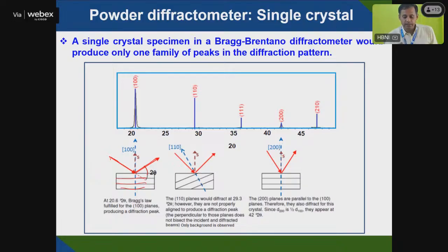A single crystal specimen in Bragg-Brentano diffractometer would produce only a family of peaks. You are getting a peak here, this peak is 100. Then you are getting a peak at 200. You are not getting 110, 111, 210, so they are empty; there is no peak there. Because only one plane is oriented to the X-ray beam, you are getting the 100 plane. Similarly, you will also get its higher order planes in the case of a single crystal.